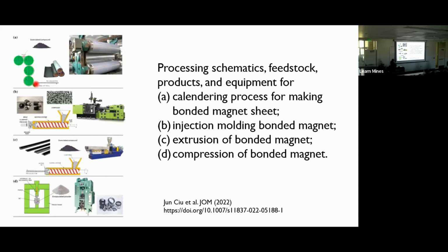Calendering is mixing and rolling into a sheet, just like we talked about with the refrigerator magnet. Or if you want to do injection molding, the molding and the tooling is the expensive part, where it's a twin screw extruder, molded and making the part. So it's all done at a higher temperature. The whole idea is you have to go close to the melting point of the polymer, mold it into the magnet and pull it out. Or the extrusion bonded magnet or compression bonded, where you are using a press under a magnetic field, and it's a simple process. June has again published, and you can see all the details after that.